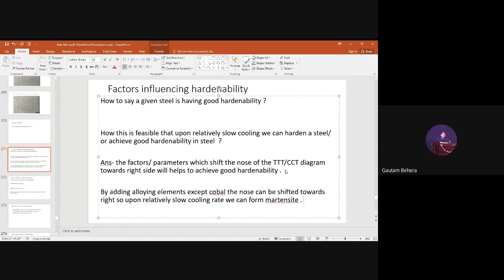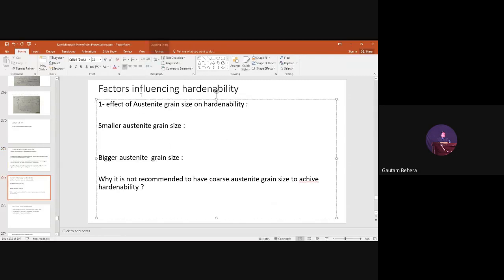So in other words, in terms of the critical cooling rate: will the critical cooling rate become slow or high if you are adding a lot of alloying elements? Slow. Yes, obviously the critical cooling rate will become slow because the nose is moving towards the right side. So if you draw a cooling curve, it will not easily touch the nose of the curve, because once it touches and crosses the nose of the curve, then transformation of austenite to pearlite may happen. Right? So we have to suppress the pearlitic formation also. Okay, anyways.